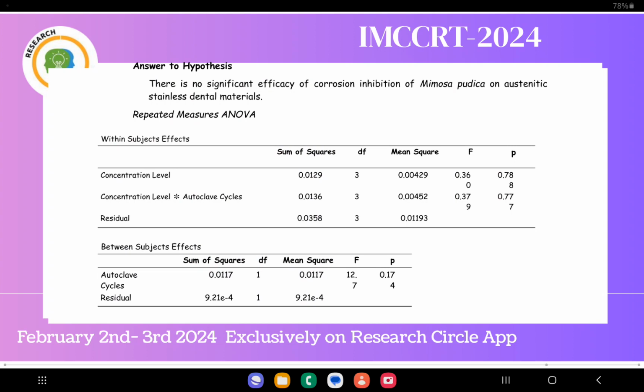The residual between subjects effects represented unexplained variance between different autoclave cycles. In summary, the analysis does not provide sufficient evidence to reject the null hypothesis, suggesting no significant efficacy of corrosion inhibition of Mimosa pudica on austenitic stainless steel dental materials under the tested conditions. The concentration levels, interaction with autoclave cycles, and autoclave cycles alone did not exhibit statistically significant effects on corrosion inhibition.